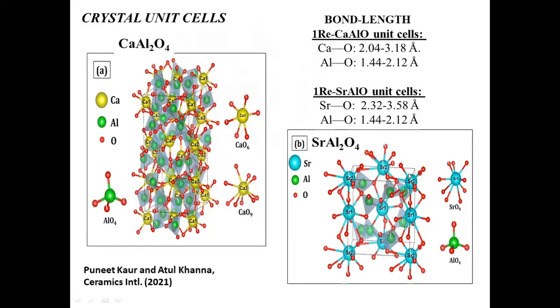So we get a single phase material by simple solid state sintering method. This is the structure. This shows the unit cell, the monoclinic unit cell, and the short range structural units. AlO4, that means the aluminum ions exist in tetrahedral coordination, and the coordination number of calcium is either 6 or 9. So once you do Rietveld analysis, you can model the structure of a material by giving the unit cell and the atomic position coordinates in some software like VESTA.